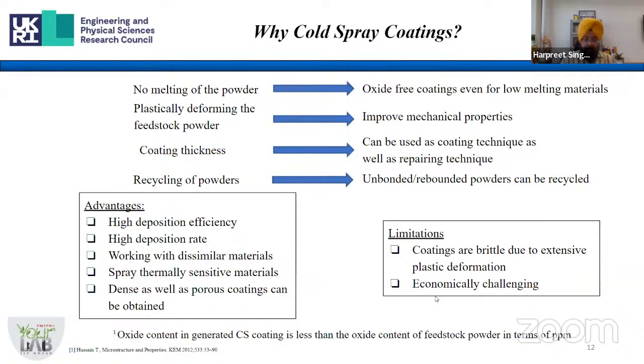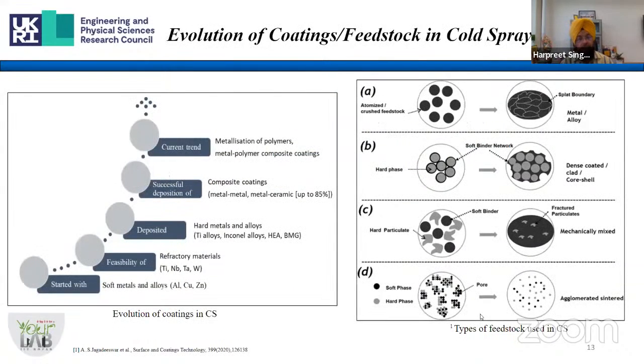The oxide content in the generated CS coating is less than the oxide content in the powder. Now, this is an interesting observation by one of the papers. So probably it is because even if your powder has some inherent oxide layers, they will break down when they impinge on the surface and so on.